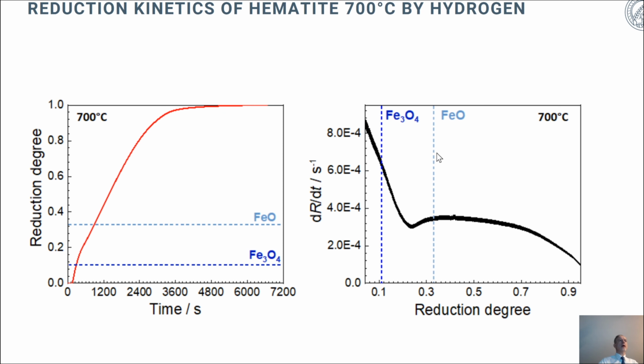it is slow. And we see that particularly at the beginning, the reduction is very fast when you reduce the hematite into the next oxidized states, which is the spinel, namely the magnetite, Fe3O4. And the by far slowest and longest reduction takes place in the transition of this magnetite at 700 degrees centigrade into the wüstite, and further from the wüstite into the iron, of course. So the kinetic bottleneck is, so to say, the reduction of the wüstite, which makes this process really slow.